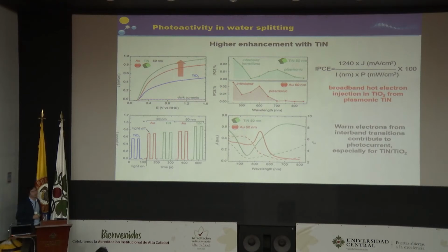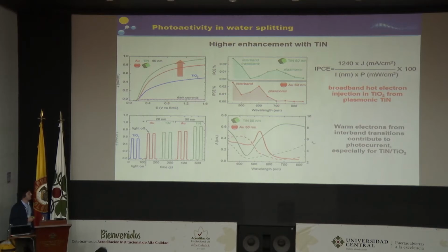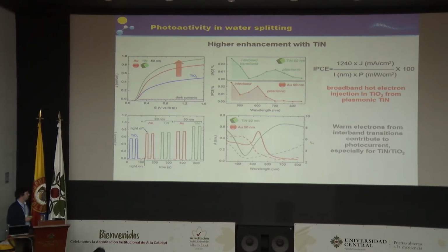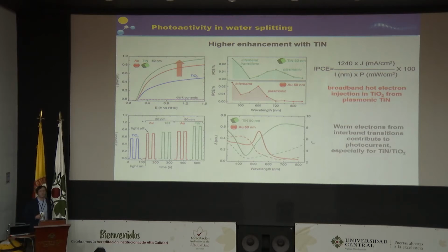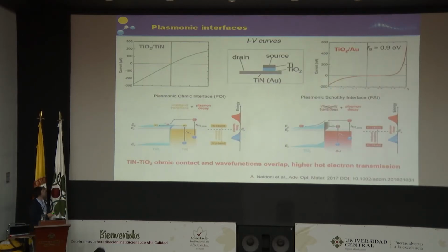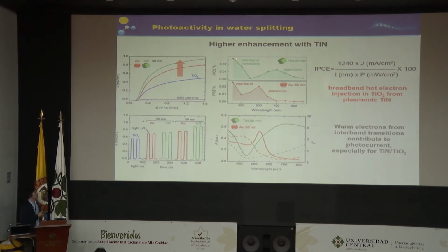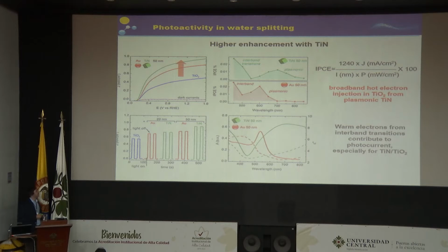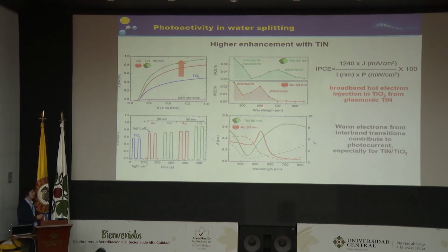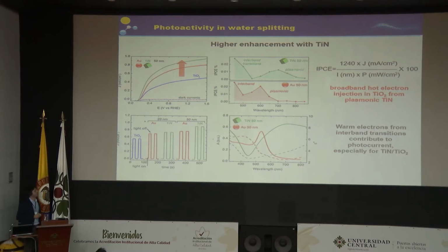So we started to go a bit deeper in this, and we measured, for example, the wavelength-dependent photocurrent and calculated the IPCE, the incident photon to current efficiency, which can give you the motivation for this increase, or what kind of photons you are using. And you can see here the spectral response of the photocurrent as a function of the wavelength. We can see that we have a current coming from the region where the surface plasmon of titanium nitride is expressed, or otherwise the gold particles. But we also have a contribution from interband transition in the metals.